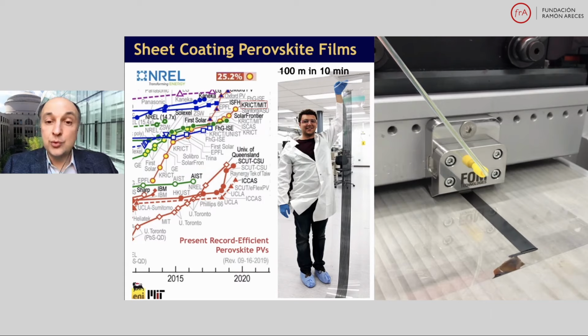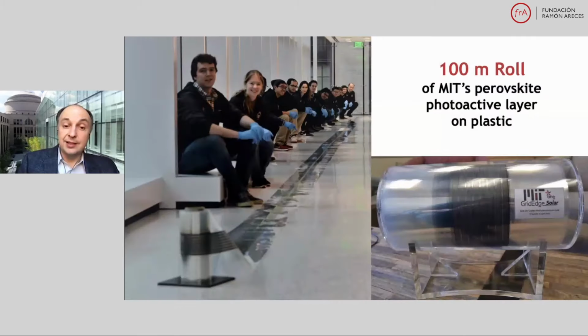And we have shown that using these kinds of perovskite materials, you can achieve world records. Earlier this year, we held a world record of 25.2% power conversion efficiency that nearly matches the best silicon performance and certainly exceeds what commercial silicon right now provides. The record has been slightly improved this summer by our colleagues from Korea, that now I believe is 25.6%. However, the goal of this work was not to set new records. The goal of this work is to make large area, simple ways of making solar cells.